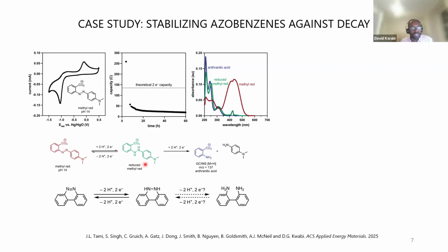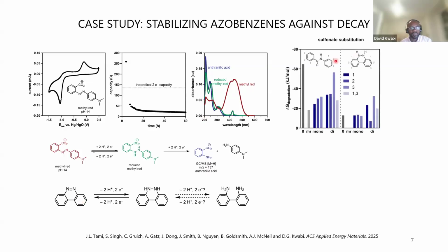And so we hypothesized that by adding an extra bond between these two aryl groups, we would stabilize the molecule against this cleavage process. And so we used density functional theory, or atomistic calculations, to calculate the rate of degradation, or the free energy of degradation, for this new molecule. This is a benzocinnoline, and this is an azobenzene. So for the benzocinnoline, we looked at the free energy of degradation predicted by atomistic calculations, and we found that it was a lot less negative, so a lot less likely to happen thermodynamically.